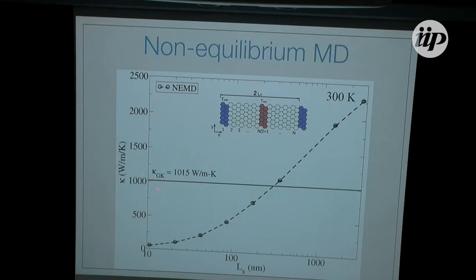The problem is that we had equilibrium molecular dynamics results from before these simulations that gave us a thermal conductivity of about 1,000 watts per meter Kelvin right here. So we were very confused when we saw this, and we thought, well, maybe the simulations are wrong. So I redid the simulations using the reverse method, the one where I swap the velocities, and I get exactly the same results. Look, the points are almost on top of each other. They have error bars that are smaller than the points.